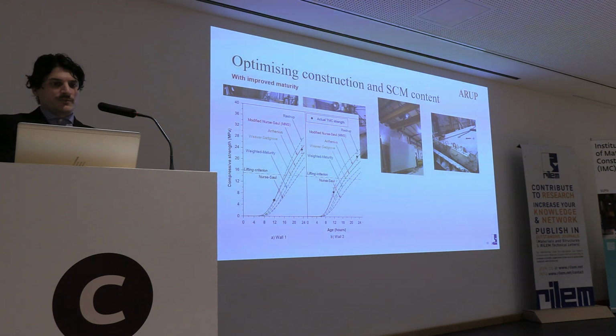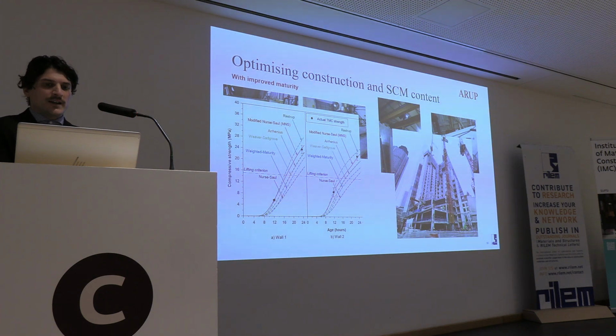So we were able to produce, with an optimized process, mixes with 50% slag, for example, for use in precast concrete, which was unprecedented. But also in in situ high-rise construction. This is an example from a 200-meter tall tower in the city of London, where we employed this method to maximize the amount of SCMs in the concrete, ending up for the core walls with a 16 to 24 hour lifting strength, as that was a jumping formwork process.